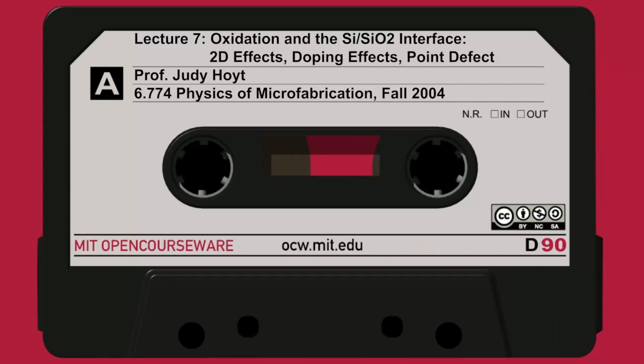The other thing is look at it as a function of temperature. At 1200 degrees, it's pretty darn flat. 1100, almost flat. So at those temperatures, the oxidation rate doesn't seem to depend very much on the curvature of the cylinder at all. It's oxidizing equally rapidly. But at low temperatures, if I go down from 1100, 1000, right between 1000 and 900, you get a big retardation in the oxidation rate. So there's a much more pronounced effect when you're at low temperatures.